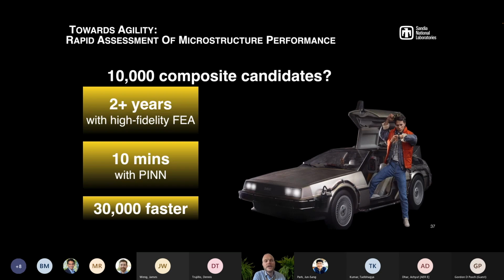And so in terms of acceleration, using this type of physics-informed architecture, you can evaluate, again as an order of magnitude, 10,000 composites in about 10 minutes, as opposed to two plus years if you were to use high fidelity finite elements. So again, in this case, it's not necessarily a 30,000 times plus acceleration, but it's still a 4 order of magnitude acceleration.